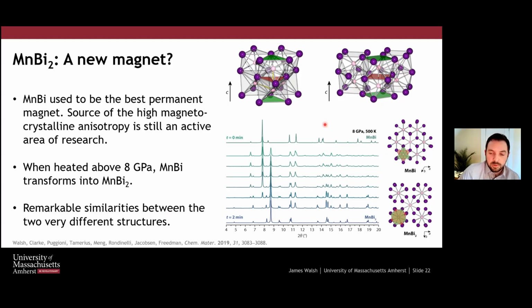What's interesting about this is that we see these remarkable similarities between these two pretty different structures. In both cases, we have these linear chains of manganese atoms along the C-axis. You can see that here as well. They both are surrounded by a different number of bismuth atoms. This one's surrounded by 8 nearest neighbors, this one's surrounded by 6. But they both share this alternating pattern of the top and bottom faces. That's kind of an interesting thing to point out. And so it's possible that this is a new permanent magnet material. Unfortunately, it doesn't quench. Just like the iron bismuth, we lose it around 3 GPa.